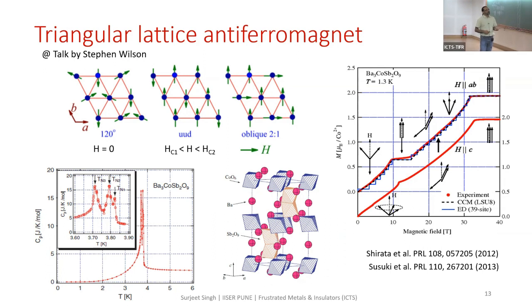So triangular lattice antiferromagnet is expected to show this 120-degree ordering, which is what you would see even with classical spins. But what distinguishes a spin half or a spin 1 triangular lattice antiferromagnet is the behavior in the presence of a magnetic field, where you're expected to see a cascade of phase transitions. And the most sought after transitions is this up, up, down state. This would also appear for a classical spin, but only for one magnetic field, because it will be some state in passing, right? But here you have this persisting over a field range, which extends from HC1 to HC2.